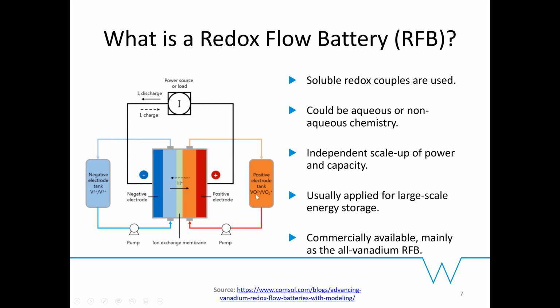For example, you have vanadium 4 and 5 oxidation states on the positive side of the battery, and vanadium 2 and 3 on the negative side. These are all soluble in sulfuric acid media. Because of this, you can independently size the capacity, based on the size of the storage tank, to the power output, which is more dependent on the electrodes and the stack and the number of stacks you can have in the cell.